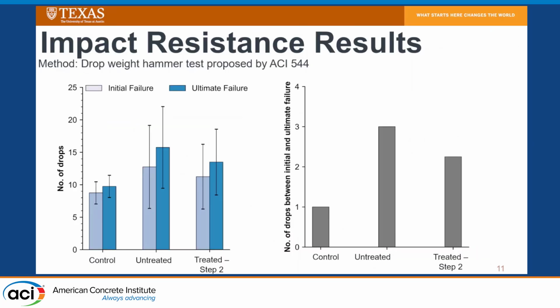We were also very interested in impact resistance results, again, because we were looking at this with the motivation of using this for applications in which you're trying to increase toughness. And we used a drop weight hammer test proposed by ACI 544. Essentially, you have a drop hammer, you have your sample, you give it a certain number of blows, and we decided to look at both initial and ultimate failure.